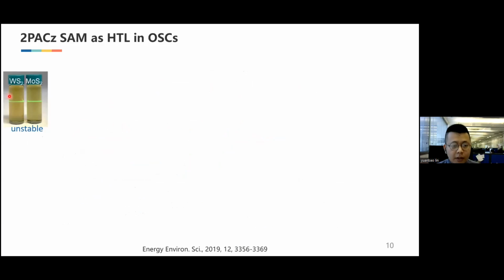But why I didn't continue with the 2D material is because this suspension is unstable. You need to store it at low temperature. Otherwise, the 2D material nanosheets will aggregate again, and we can see some powders at the bottom.